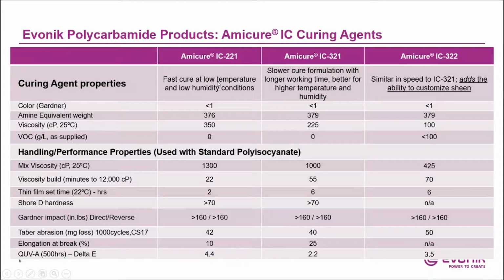IC221 is a fast cure at low temperature and low humidity conditions. IC321 has lower reactivity, so it's a slower cure, has longer working time, and is better for higher temperature and higher humidity. And Amicure IC322 is more similar to IC321 in reactivity. However, what it does is add the ability to customize the sheen.